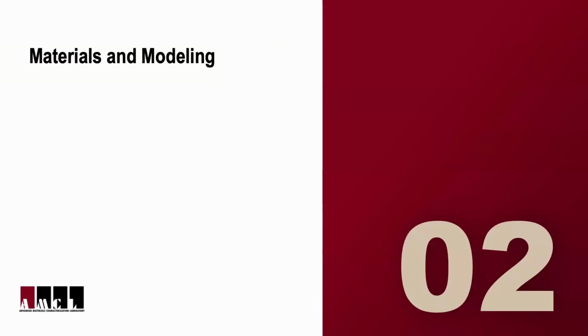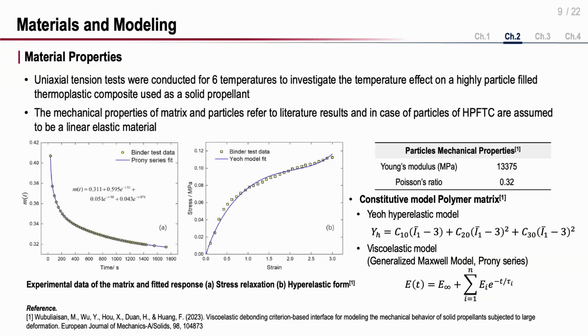And next is materials and modeling. In our study, we conducted uniaxial tension tests for 6 temperatures. And for the mechanical properties of matrix and particles, we referred to literature results. For particles, linear elastic properties were used. And for the polymer matrix, the coefficients of the hyperelastic model were used. And this is the equation of the hyperelastic model. And regarding viscoelastic properties, the coefficients were derived from a Prony series based on the generalized Maxwell model.